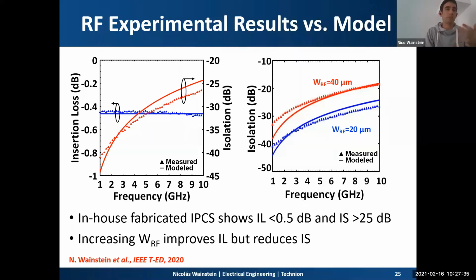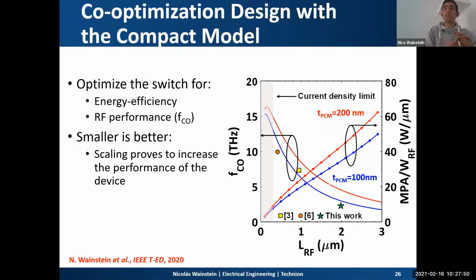It's obvious, but it was worth mentioning, increasing the width of the RF contacts will improve the insertion loss, but at the same time will reduce the isolation, as you can see in the right panel. The main advantage of this model, in conclusion, is that this model allows for co-optimization design of the switch to achieve high RF performance and low power.